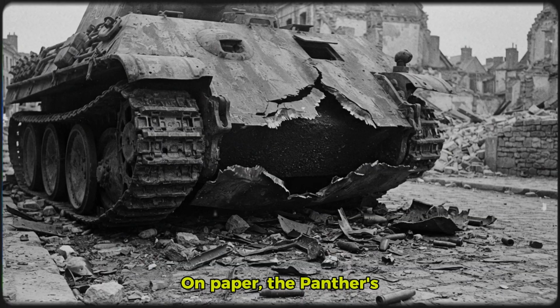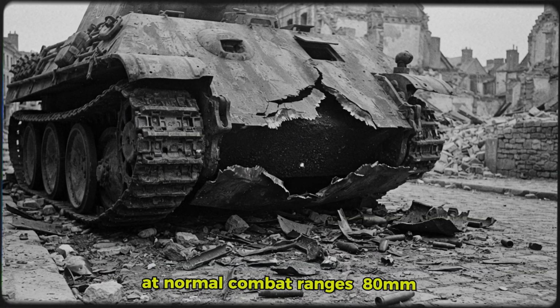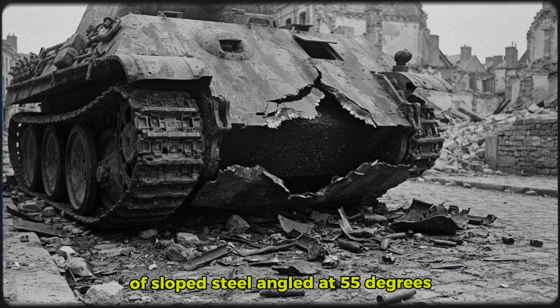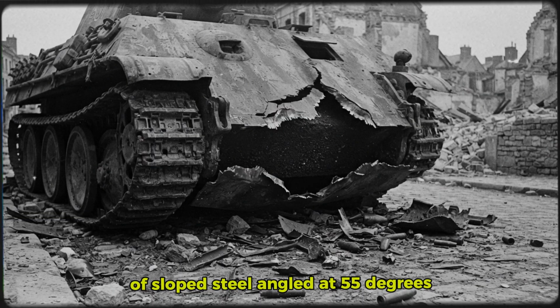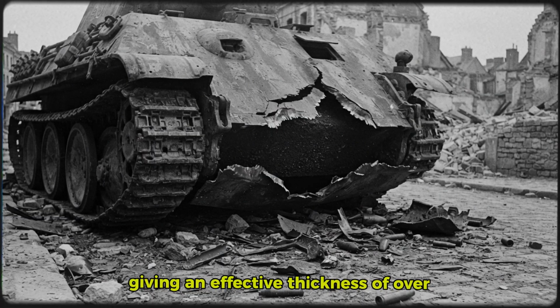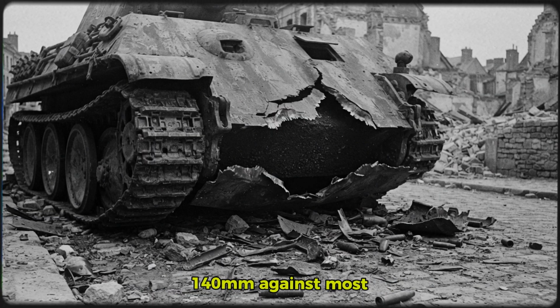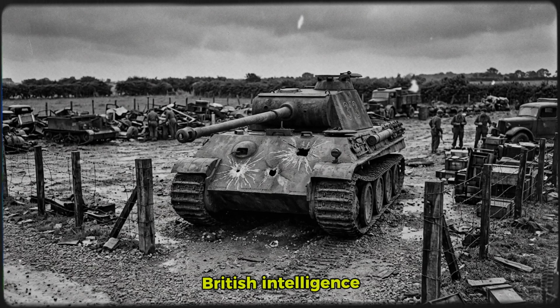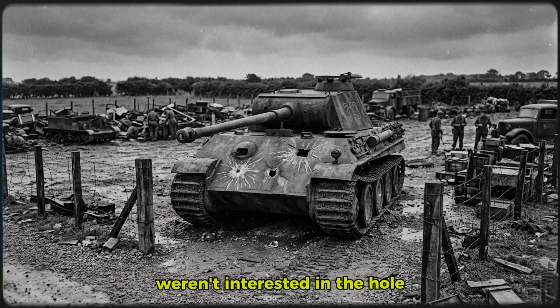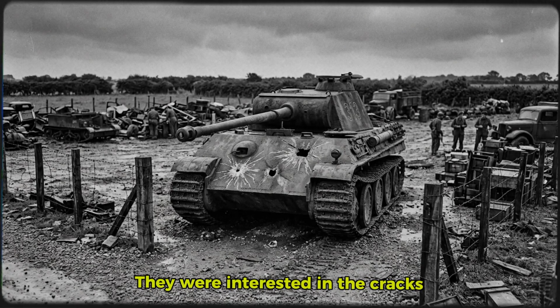On paper, the Panther's frontal armor was close to impenetrable at normal combat ranges, 80 mm of sloped steel angled at 55 degrees, giving an effective thickness of over 140 millimeters against most Allied guns. British intelligence officers who examined the wreck weren't interested in the hole. They were interested in the cracks.